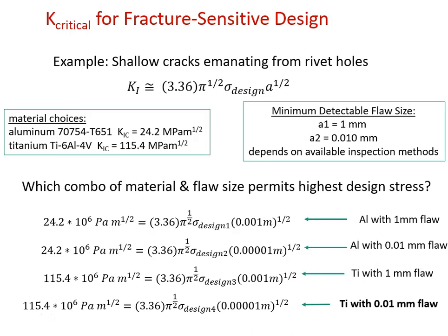If the design stress in that case caused the right-hand side of the expression to exceed 24.2 times 10 to the 6 pascals meters to the 1/2, we would have spontaneous crack propagation in that design, and it would fail by fracture. So we can continue that same argument using a different flaw size or a different K1C.